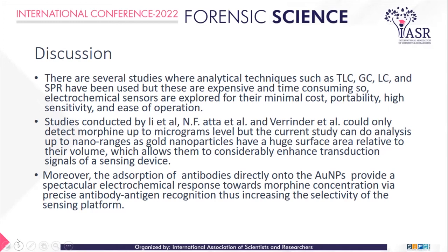Moreover, there are several studies conducted by Lee et al., NF et al., and Verrinder et al., but they detected morphine only up to microgram level. However, in the current study, we could detect morphine up to nanoranges, as gold nanoparticles were in use, which increase the surface area. The size of the nanoparticles is decided such that the relative surface area to volume ratio gets increased, and as a result it increases the sensitivity of the device. Moreover, antibodies were absorbed onto the surface after gold nanoparticle modification, which increased the selectivity of the sensor by detecting the analyte of interest, that is morphine, by antibody-antigen recognition.